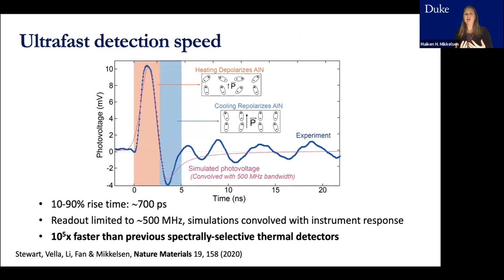So remember with the pyroelectrics, I showed you often it's in the millisecond time scale. So it's a very slow response, and it has really limited the commercial applications. So what we found here was that we have an ultra-fast detection speed. The way that we measure that is we use, again, a pulse laser that hits the sample here at time 0. And then we are just measuring the photovoltage as a function of time to map out this response.